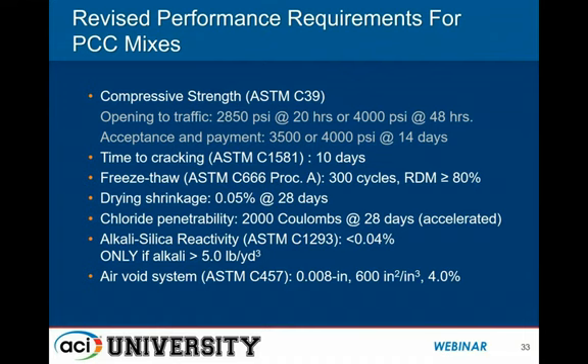So here's where we wound up revising the performance requirements. And this is a purely performance-based specification. We have opening to traffic strength and acceptance for payment strength at 14 days. And these are the two strength criteria that were emphasized. Once you get the opening to traffic strength, really there was no concern regarding getting the later age strength. I don't think we ever had any issue getting that in less than a few days, but you'll notice it's not really required until 14 days.